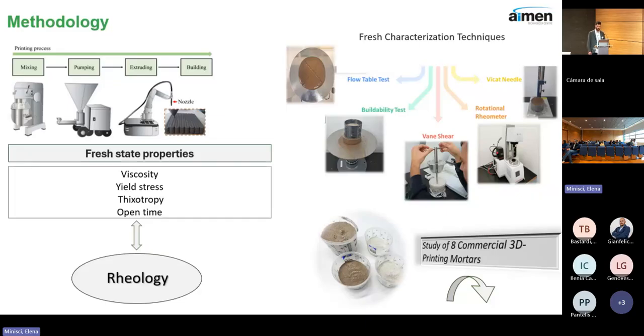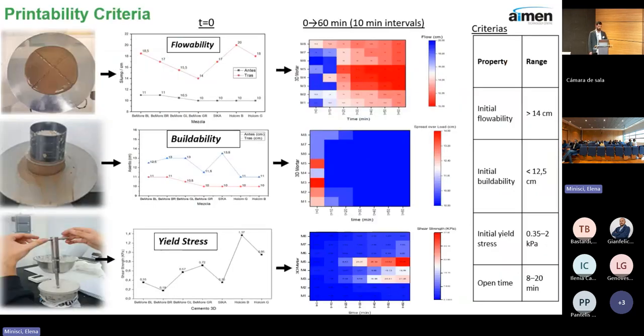And through different fresh characterization techniques, for example, flow tests, buildability tests, and the Vicat needle, and we complemented all of this work with a rotational rheometer. So we did this work, and we are now at a point where we know exactly what we need to achieve in order to have a printable cementitious material. We have some criteria in terms of initial flow, buildability, and yield stress. And we also study the evolution of these rheological properties over time, up to 1 hour at 10-minute intervals, in order to establish also the open time of our materials.